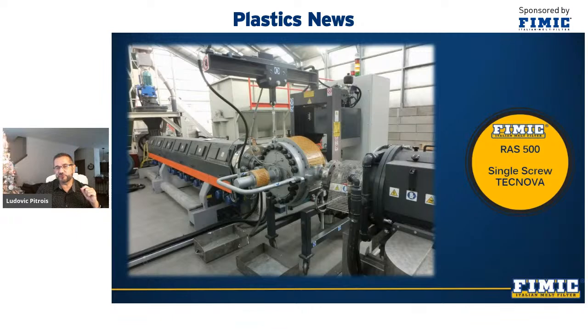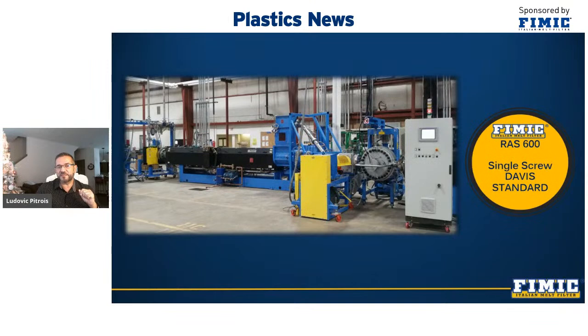In the Tecnova extruder, unwashed PP flake is processed at a capacity of 3,300 pounds per hour with a RAS 500 filter. This capacity is achieved because the customer uses a filtration of 500 micron with a perforated punch screen. In this Davis-Standard extruder, they obtain 4,000 pounds per hour in unwashed low-density PE with a RAS 600 filter. Most of our installations in North America are on DS extruders.